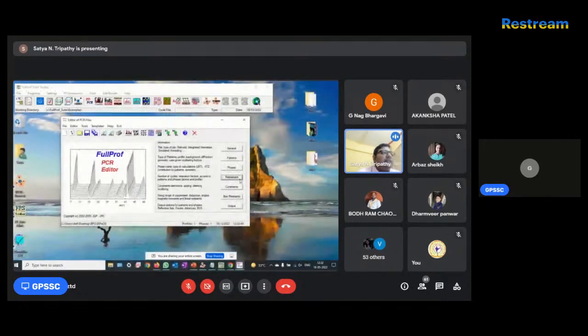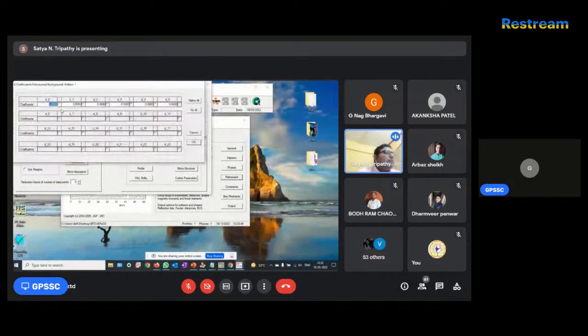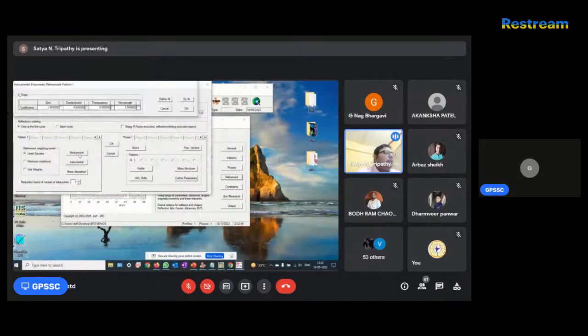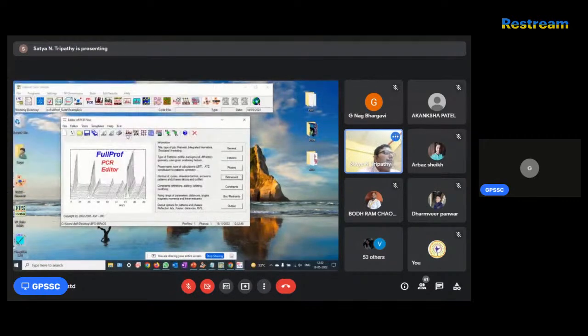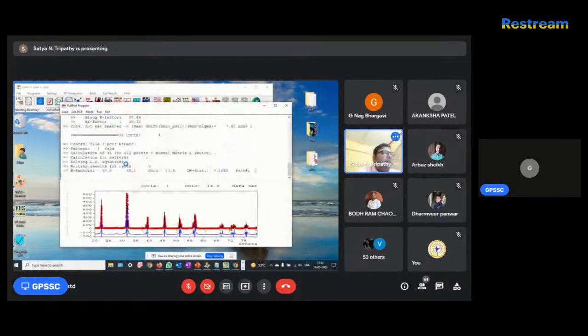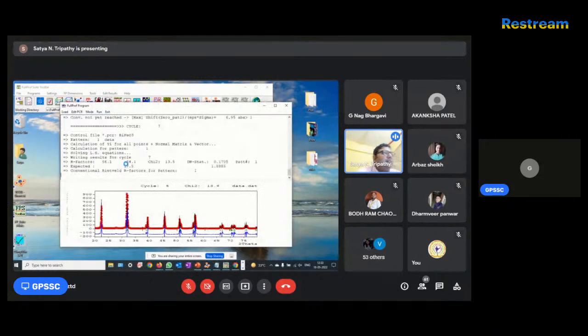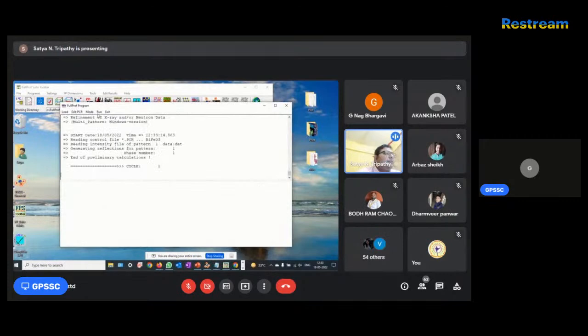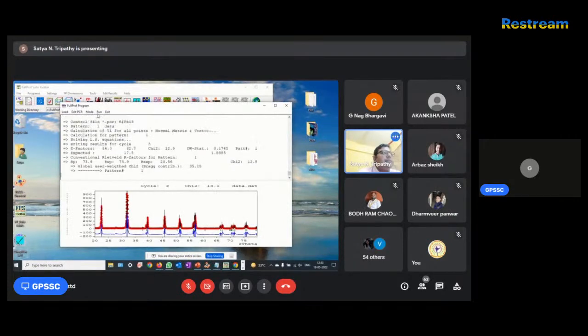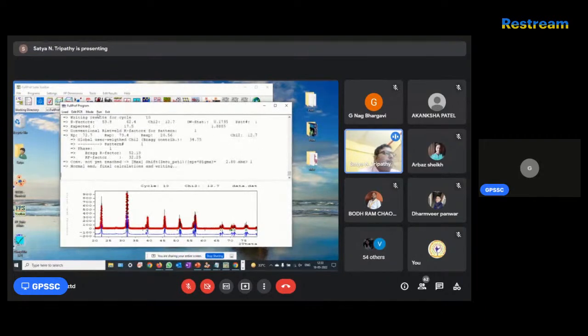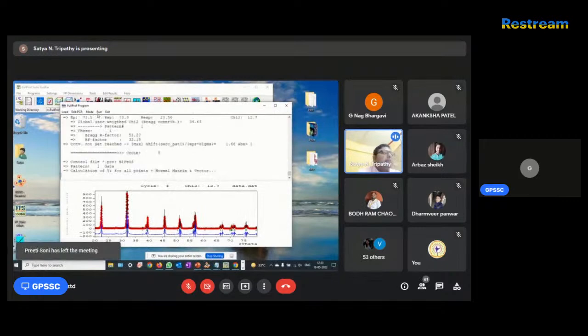So you reload. Next you go for background. You just try to fit the first parameter. That's enough. Okay, first parameter, and in instrumental you select 0. So if you do that, you save it. Let's see what will happen. This is very important. You can see now what instrumental corrections it is adjusting. My background is actually fitted correctly because I refined the first parameter. So until it converges, I'll basically run the data.